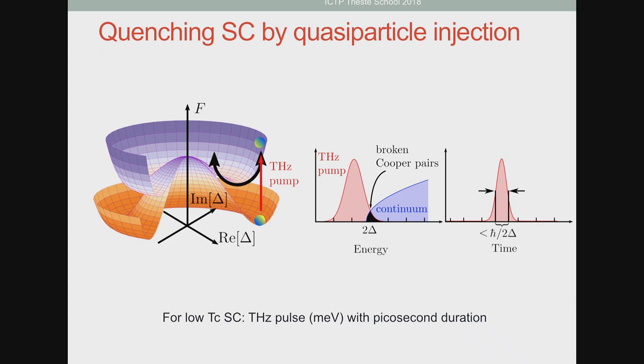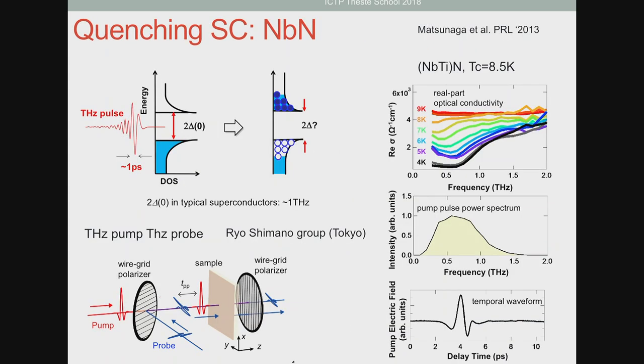For typical low Tc superconductors, this requires pulses in the milli-electron-volt energy range, so in the terahertz region, with picosecond duration. This experiment was actually done. Here I'm showing you an experiment done on niobium nitride. It's a terahertz pump, terahertz probe measurement. You shine an intense terahertz pulse. This is the spectrum of this terahertz pulse. It's roughly centered around 1 terahertz, and 1 terahertz is roughly 3 millivolt. And this is essentially a single-cycle pulse in the time domain, with a typical width of about 1 picosecond.